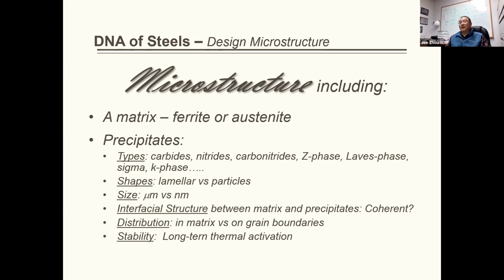The precipitate is also about types and shapes; it can be lamellar, particle, or needles. The size goes from microns down to nanometers. It is also influenced by the interface structure between the matrix and the precipitates, either coherent, semi-coherent, or non-coherent, and by how the precipitate is distributed, either in the matrix or on the grain boundary. One big issue on precipitates is the thermal stability, and this also influences the creep behavior.